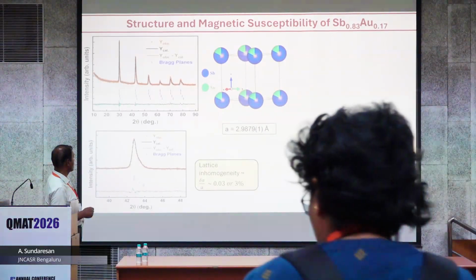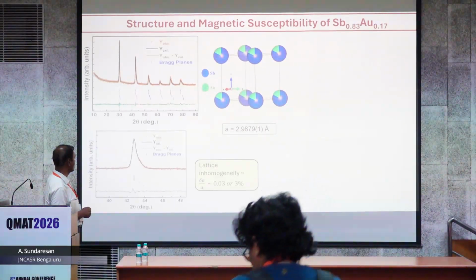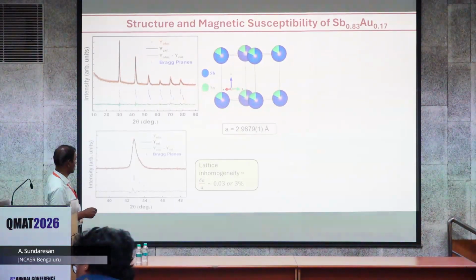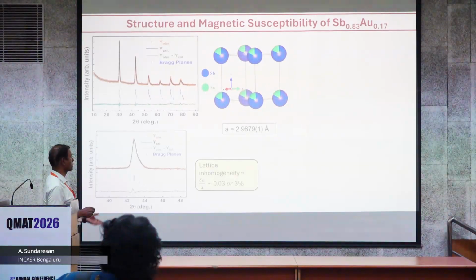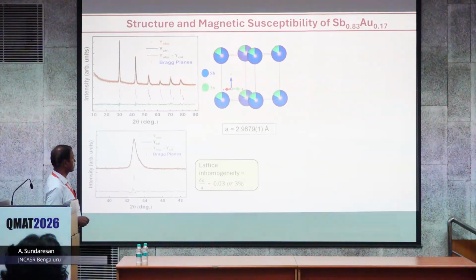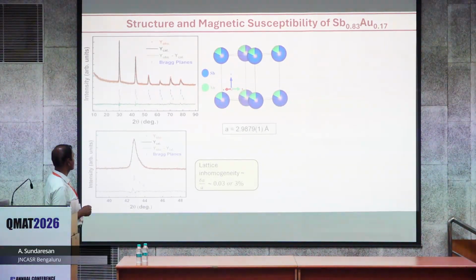When you look at the X-ray, you can see this corresponds to the simple cubic, but chemically disordered, as you'd expect from this composition. If you look more carefully at the peak shapes, there is an asymmetry on all the peaks.